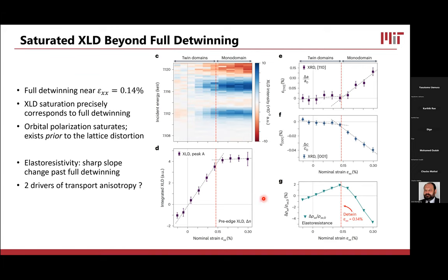Can I follow up very quickly? I like your work, it's very nice. Suppose I want to see fluctuations in the orbital channel, in particular the anisotropy in this particular symmetry channel over some extended energy range. Neutron has done that all the way to 100 or 150 meV, right? So what's the technique one could envision revealing that information in the orbital fluctuation sector? Because polarization at the end of the day is static.